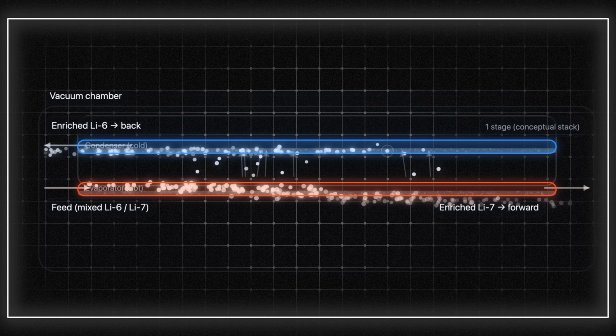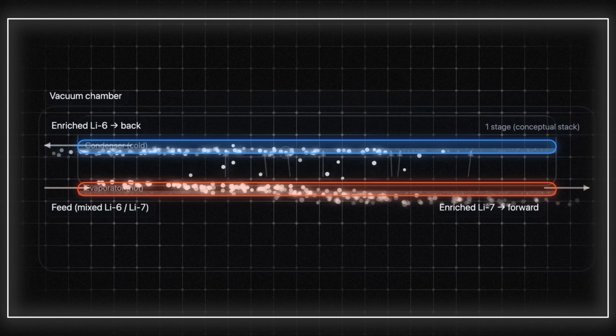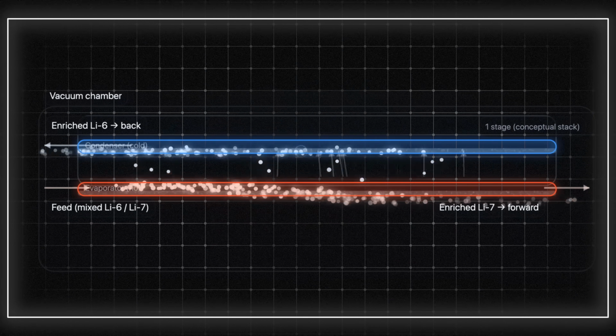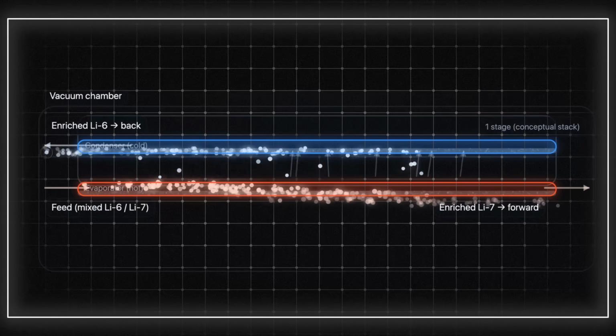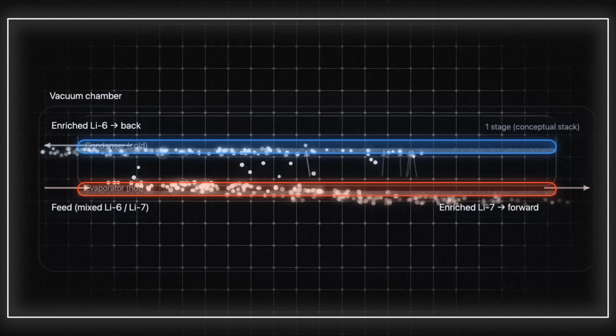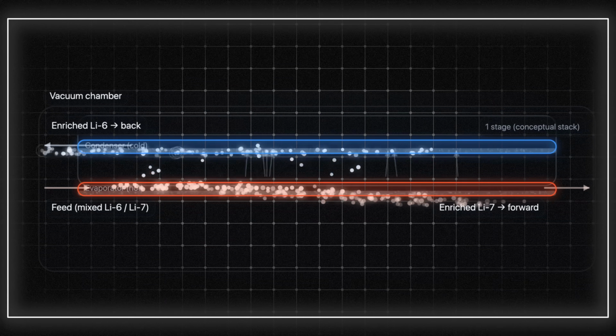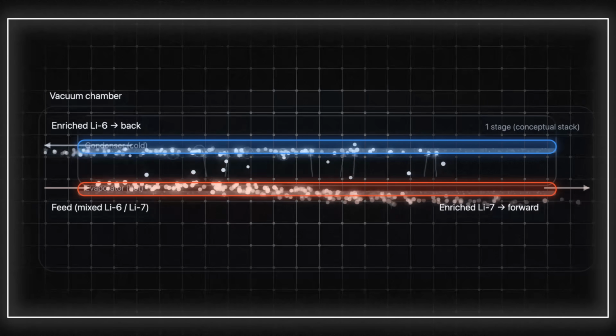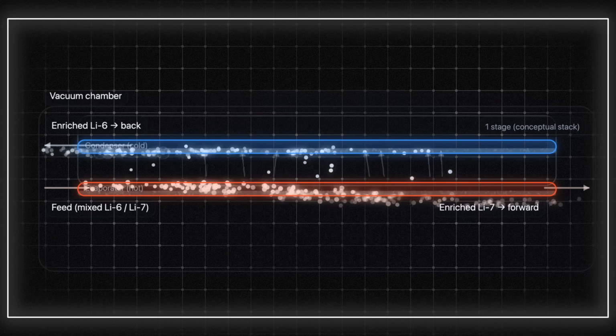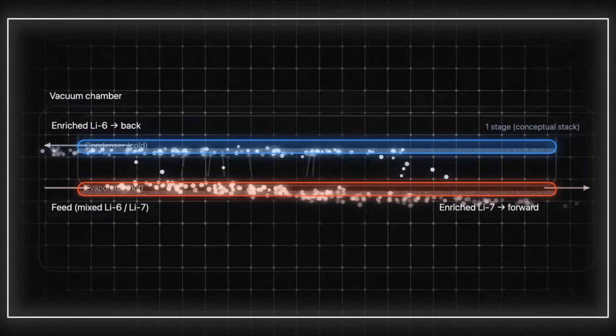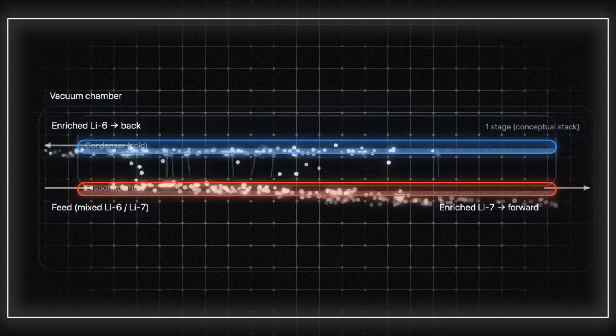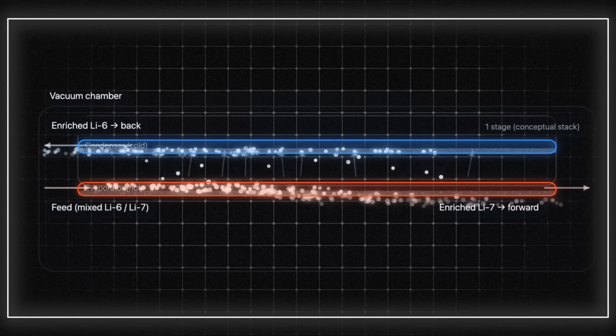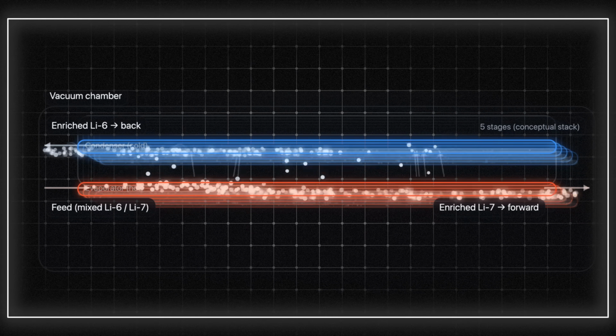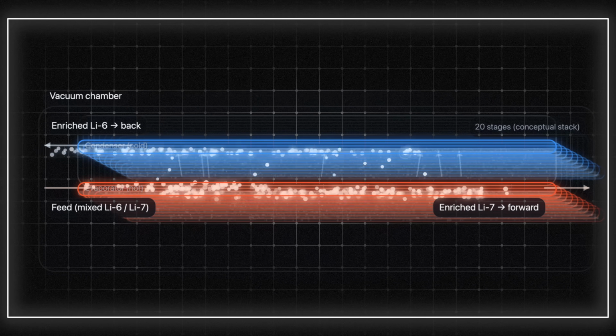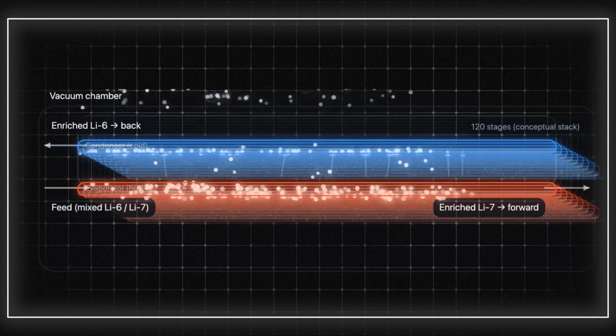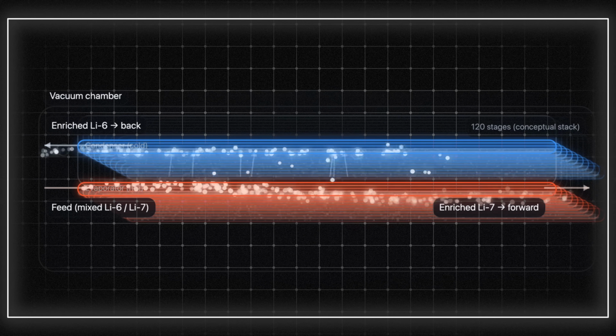Here's how it works. They use a vacuum chamber with a heated bottom plate, the evaporator, and a cooled top plate, the condenser. Instead of complex pumps or gravity feeds that require precise leveling, they use capillary members to transport the molten lithium. The lithium-6 is lighter, so it evaporates slightly faster. It condenses on the top plate and flows backward via the wicks, while the heavier lithium-7 stays on the bottom and flows forward. By stacking hundreds of these stages in a single unit, they can separate the isotopes without using a single drop of mercury. And the best part, it's a continuous flow system.